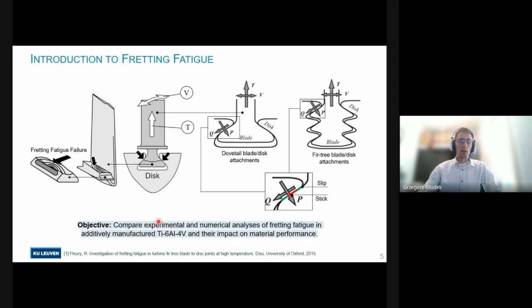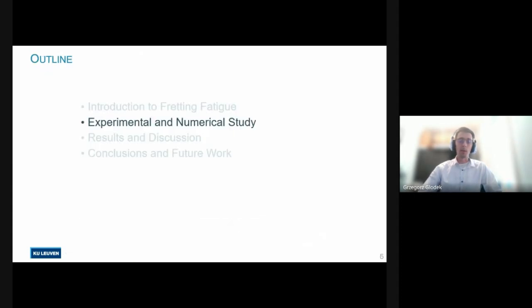So starting with a short introduction to fretting fatigue, it occurs due to changing external forces, for example, caused by changes to the RPM of the turbine engine, or due to vibrations, and those generate cyclic contact forces and also relative displacement between two parts under pressure. In this case, it's the blade and the disc in a turbine assembly. Now, the most damaging condition takes place when slip occurs at the edges of contacts, but we have a stick condition in the middle, and this results in significant damage to the contacting surfaces, which is greatly detrimental to their fatigue lifetime.